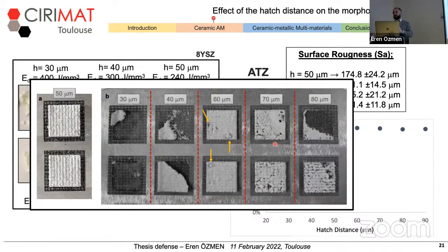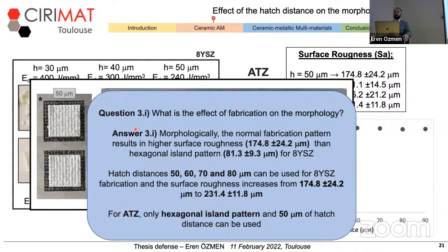When we apply different hatch distances on ATZ fabrication, we see that except 50 micron, none of the hatch distances are giving satisfying results, with pieces full of cracks and most of them showing many defects. So we can say that for 8YSZ fabrication, we have a wider parameter area, with two strategies, normal and hexagonal, for hatch distances, while we have only one pattern and one hatch distance, 50 micron, working for ATZ fabrication.